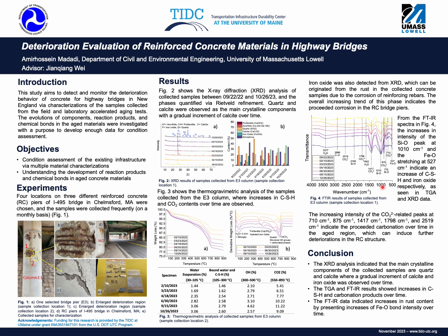This FTIR analysis also shows some carbonate-related shifts, as you can see in figure 4, at different wave numbers, for example at 710, 875 and 1417 cm⁻¹. The increasing intensity of these shifts also signifies the progressing carbonation in the aged regions, which can show the potential risks of further degradation to the reinforced concrete structures.